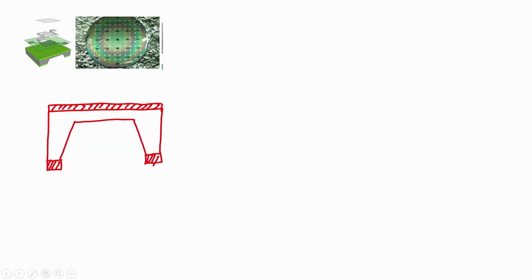I will have an oxidized wafer with a diaphragm, and this angle, we know it, would be 54.7 degree, right. Now, the next step, after we have the diaphragm, the first step on that front side would be the heater.